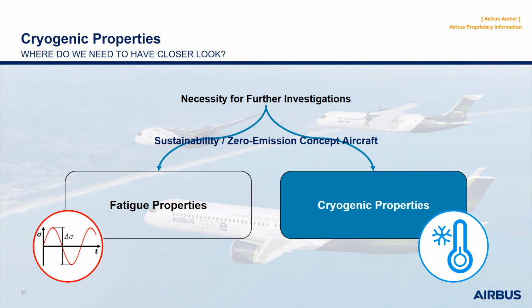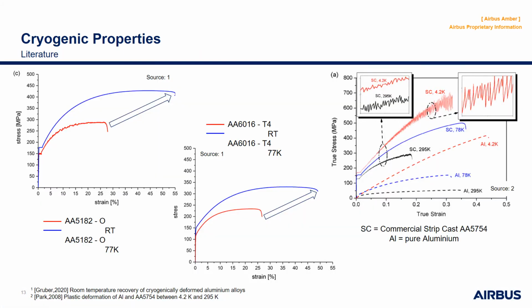So, next to the fatigue properties, a special focus will be on the cryogenic properties of our additively manufactured materials here at Airbus. From previous investigations and literature, no embrittlement of aluminum alloys at cryogenic temperatures was observed so far. As you can see here, for example, for 5000, 6000 aluminum alloy series and also for pure aluminum. Only for some states, for example T6, a minor decrease of elongation was observed so far when tested at these temperatures.